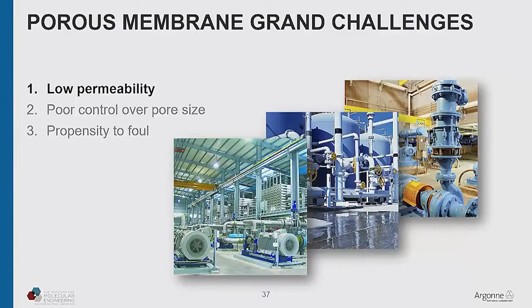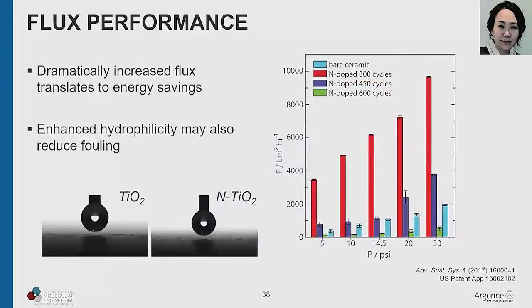Okay. What about permeability? Well, I've only got one slide on this, but we were happy when we saw this result. It wasn't an intentional one. So this is that doped titanium dioxide again. This is a plot of the flux of water that goes through this membrane as a function of the pressure that you apply, the transmembrane pressure. So of course, flux goes up when you increase pressure. And the light blue here is the performance of the starting membrane.